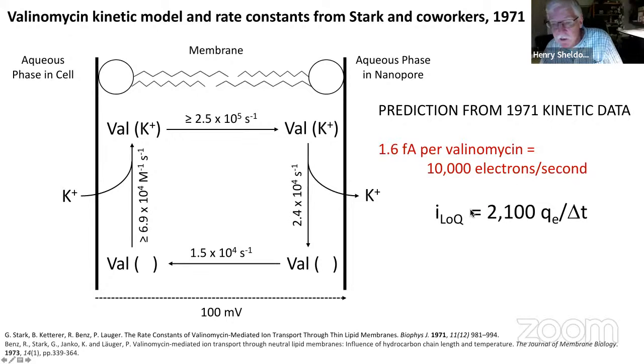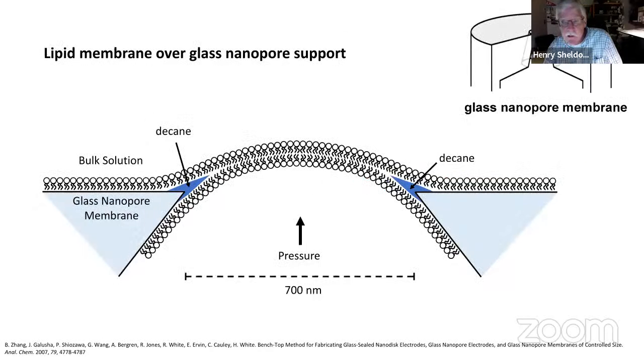So we thought this is a doable experiment because, if we're doing a measurement in a 1 second time period, this rate is greater than the minimum current that we predict you need to measure. But it's really close. This is state of the art in the literature, and it's just above the theoretical shot noise limits. So this was a sort of test case. Can you do this?